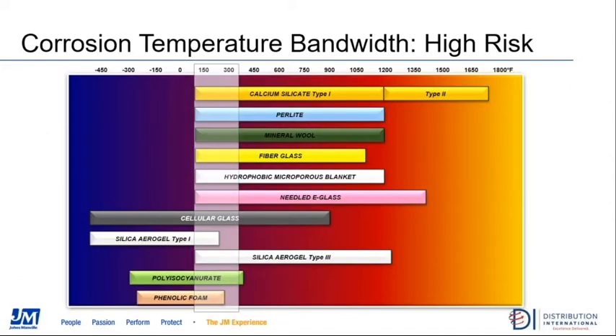So again, to review where we see corrosion happen, what we see in this graphic here is a list of pretty much all of the insulation materials that are installed out in the market today on hot systems. The white area there is what we call our high-risk corrosion band, about 150 degrees up to 300 degrees. Now, corrosion can occur outside of those ranges, but if you're installing insulation in an application that runs in this temperature, we would consider that a high risk for corrosion potential.